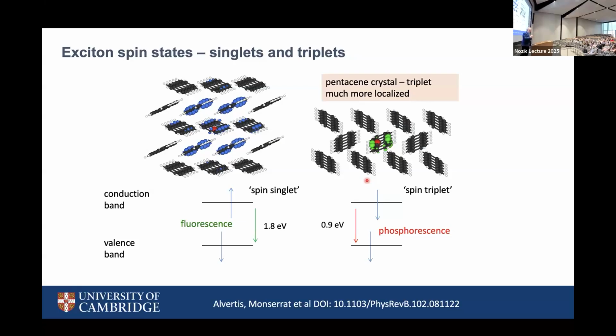And the way that the antisymmetrization of the spatial wave function then works is that the two electrons in the excitation keep well away from one another. They're never at the same place, but therefore they can condense to a much smaller object, a very, very different size, just down onto one molecule. And in doing so, it becomes much lower energy. It drops to about half the energy of the singlet exciton. So the triplet is much lower energy than the singlet.